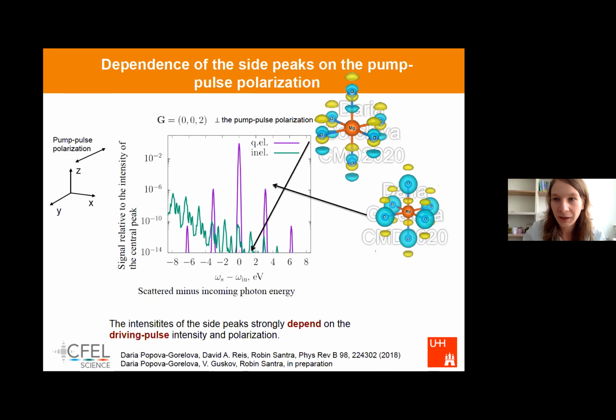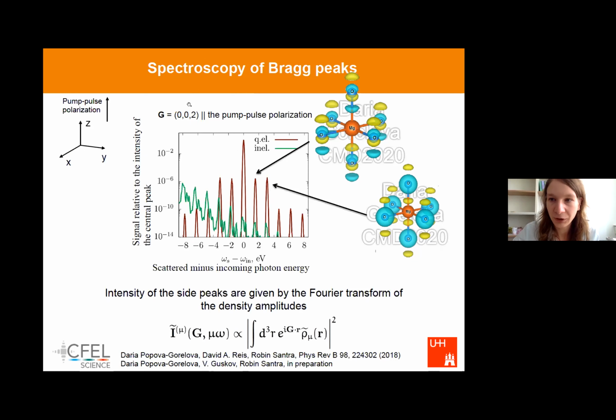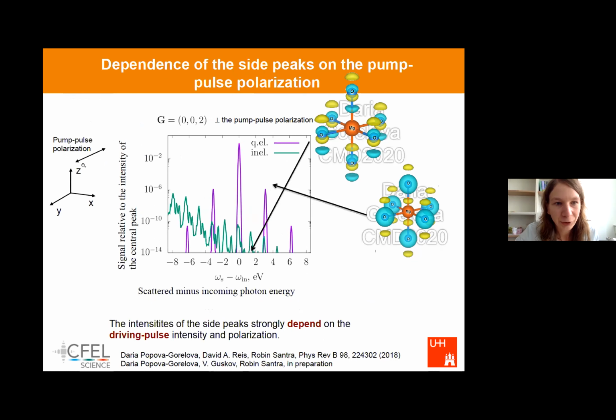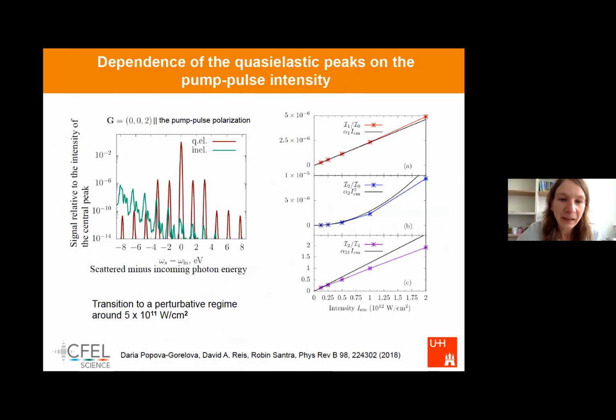Here I also should mention that this picture is for the scattering vector parallel to the pump pulse polarization. For the scattering vector perpendicular to the pump pulse polarization, we also can see interesting selection rules. All odd order side peaks disappear, while even order side peaks remain, and from these pictures, in principle, one could understand how this could happen.